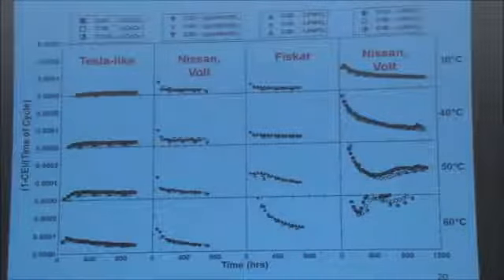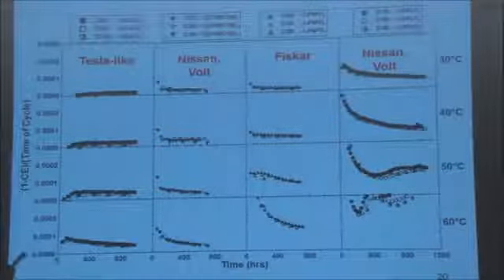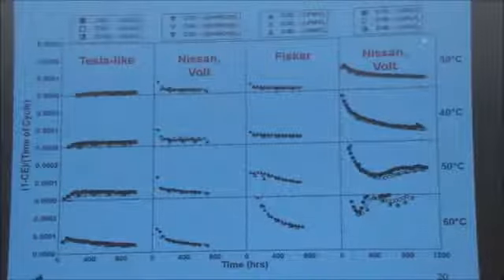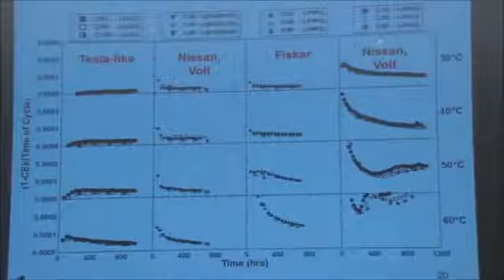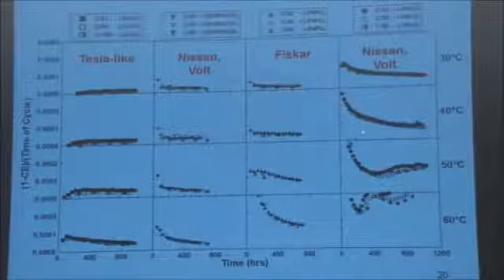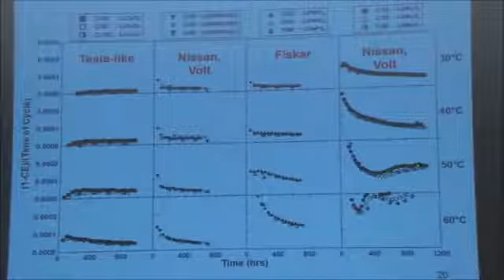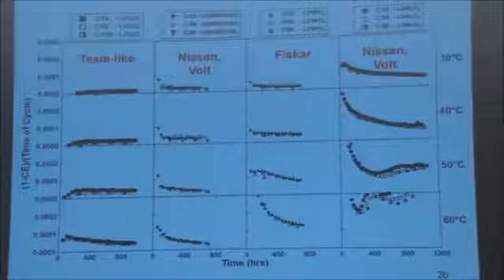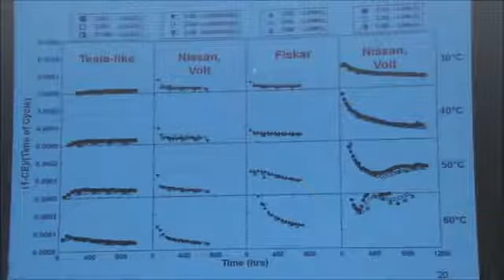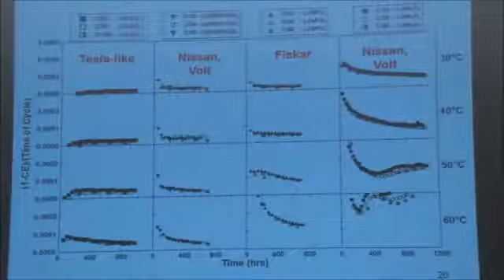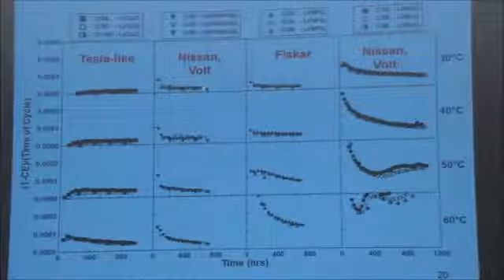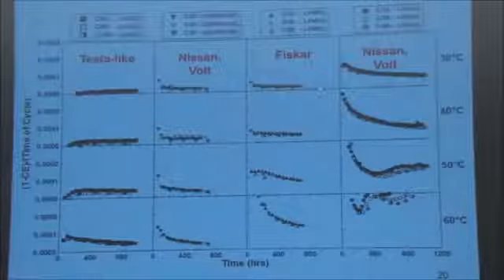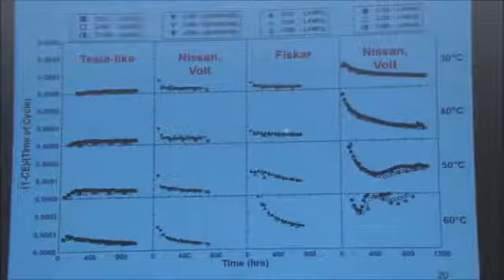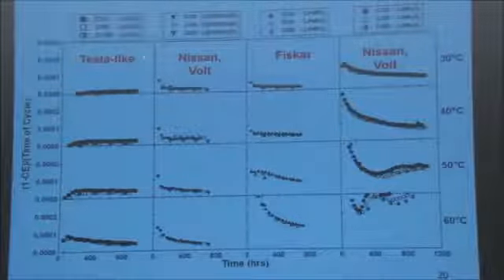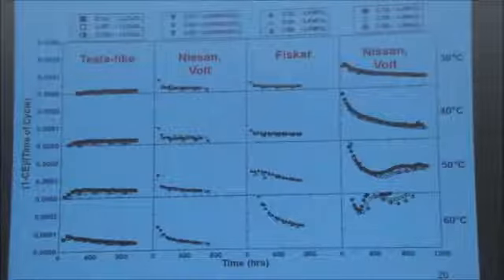So Nissan selects a blend, about 50% of this and 50% of that in their cells. And so does GM in the Chevy Volt. Nissan does not temperature control the battery pack. Lots of parasitic reactions going on at elevated temperature. It's going to lead to early cell failure. GM does temperature control their battery pack, and their packs are lasting longer than the Nissan under high temperature conditions. Fiskar, another poor choice, and Tesla has selected chemistries like lithium cobalt oxide that are very good.